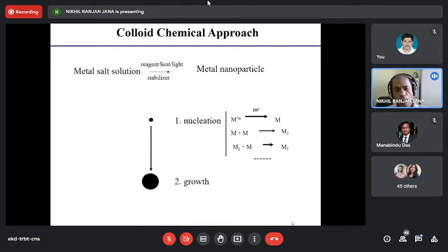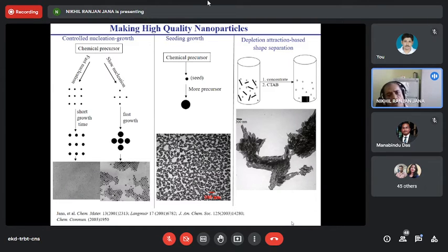So for making gold nanoparticles you start with gold salt and a reducing agent that transforms gold ion to gold atom, and then gold atoms will aggregate into clusters and nanoparticles, like I showed on the right side. Then it will form large clusters, nanoparticles, and these nanoparticles have to be stabilized with a surfactant or polymers. So a polymer or molecular stabilizer at the surface of these particles, and you will get colloidal nanoparticles. If we want to make high quality nanoparticles, meaning specific size with well-defined surface chemistry, these are some of the approaches.